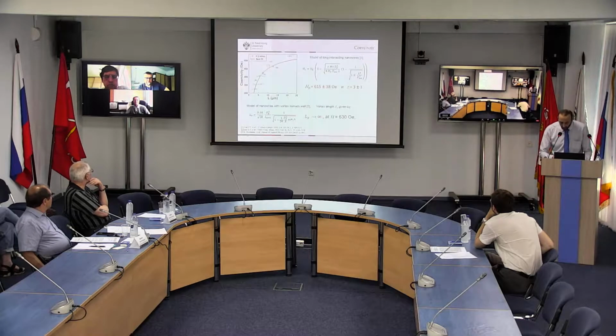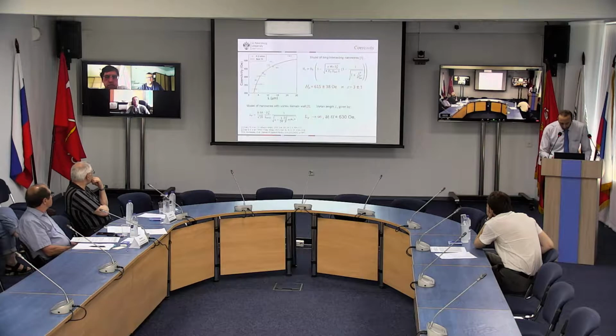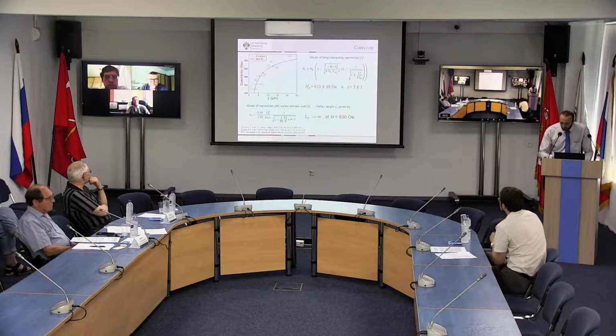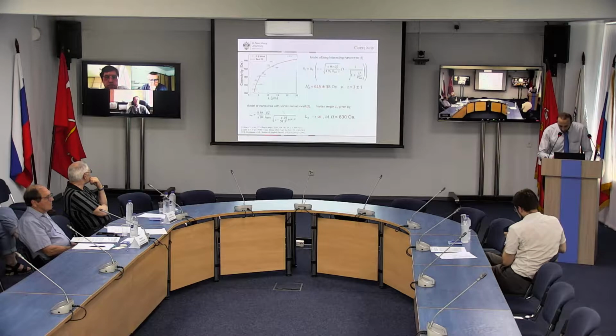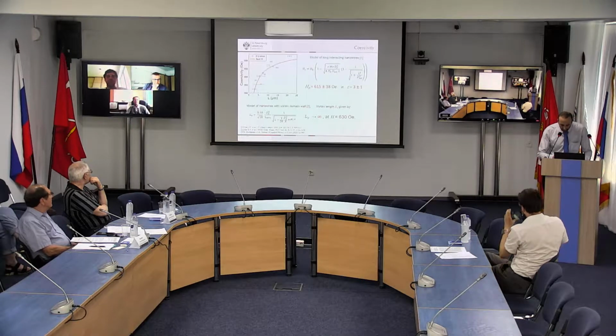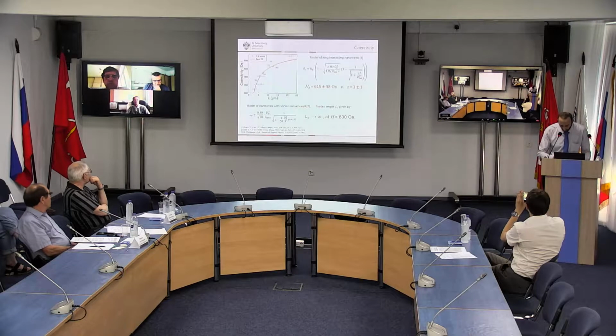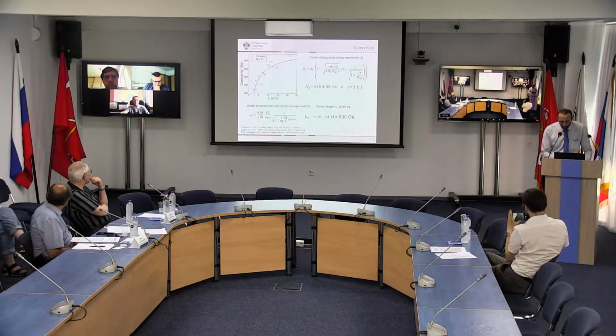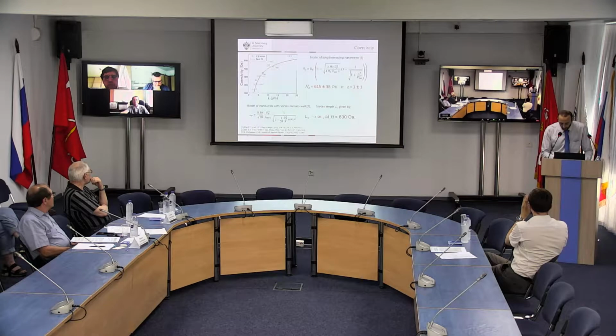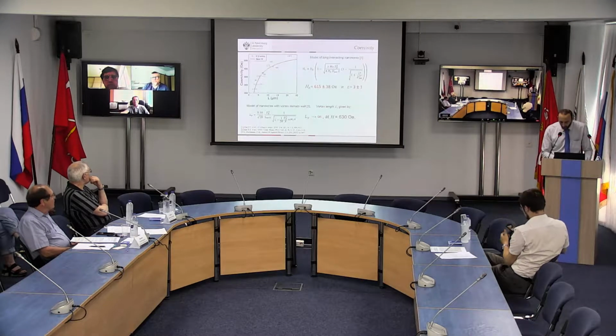Also, the coercive force of an individual wire can be calculated by the model of wire magnetization by a certain mechanism. According to this model, systems with a diameter bigger than 7 times the exchange length, which is the case in our system, could be remagnetized by vortex domain wall motion. And the field where, in the given equation, the denominator tends to 0, and thus the length of the vortex tends to infinity, could be considered as coercivity. We can see that the compatibility between both models gives us an indication of a decrease of interaction between wires. Also, that our system demagnetizes by means of vortex domain wall motion.